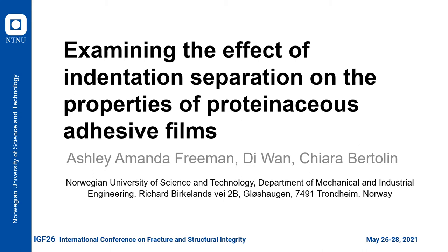Gelatin-based adhesives have been used for centuries by artists, and as the deterioration and damage of art objects are related to the chemical and mechanical properties of the materials from which they are made, we must develop a better understanding of these properties to safeguard works of art. Generally, if sampling is allowed, some millimeter-size samples are taken for chemical analysis. However, more recently with the use of nano-indentation, mechanical features have been directly extracted from millimeter-size samples taken from works of art, instead of employing the conventional method, which typically consists of tensile testing performed on macro-size mock-ups made to mimic the chemical and physical behavior of historic artist materials.